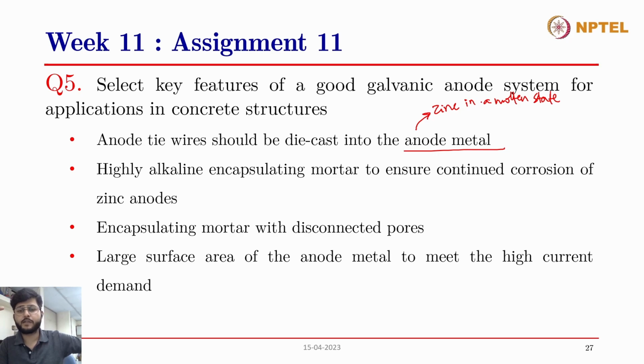And sometimes if the tie wires are not die cast in the anode metal, then what happens is, when the anode metal gets corroded, these corrosion products, that is the zinc oxide products, form around these tie wires and create expansive stresses, and that will allow for the cracking of these tie wires, and that will create a loss of connection between the steel and the zinc anodic system.